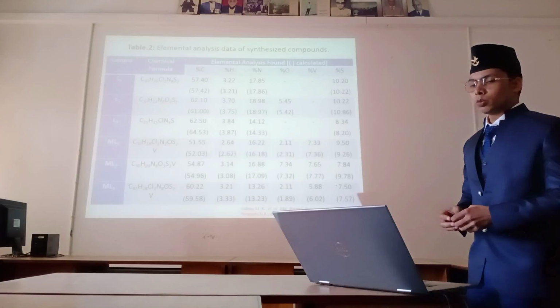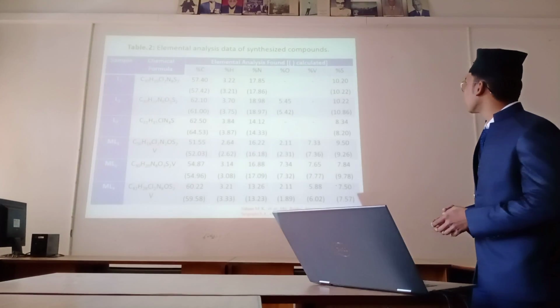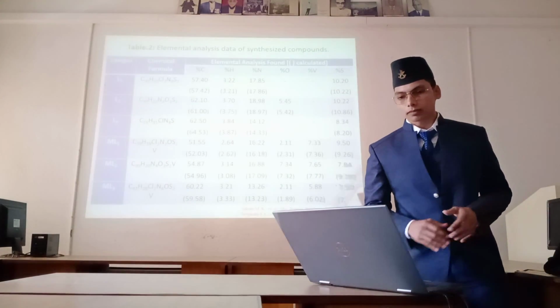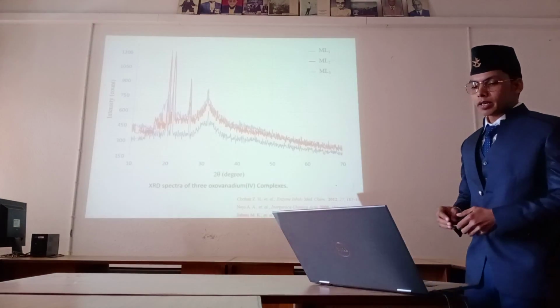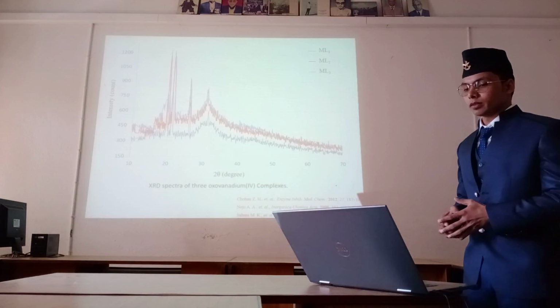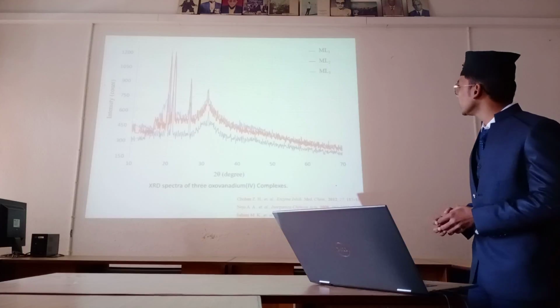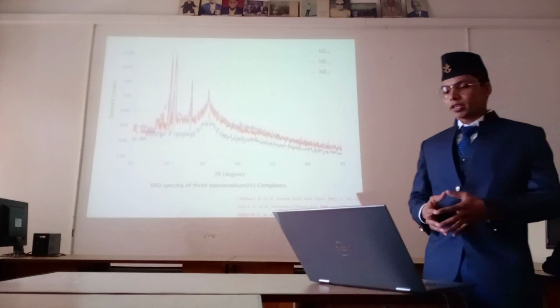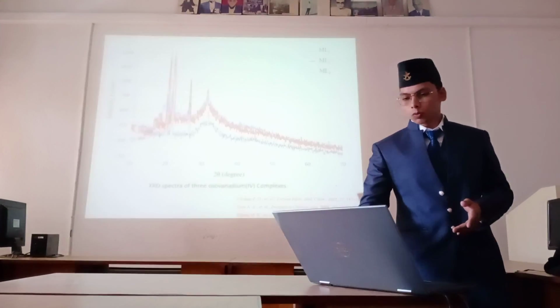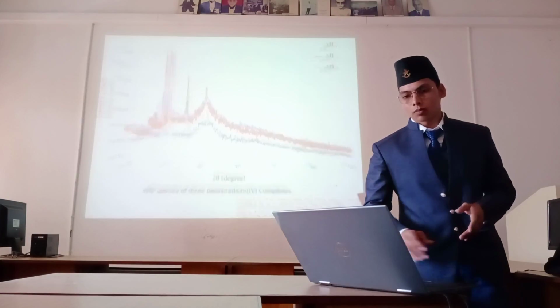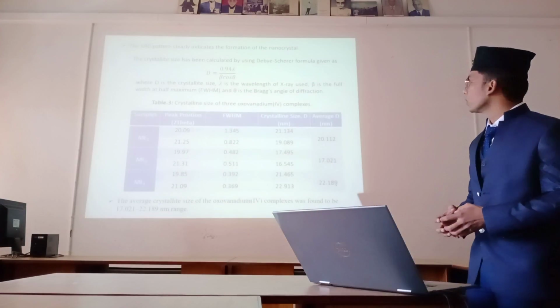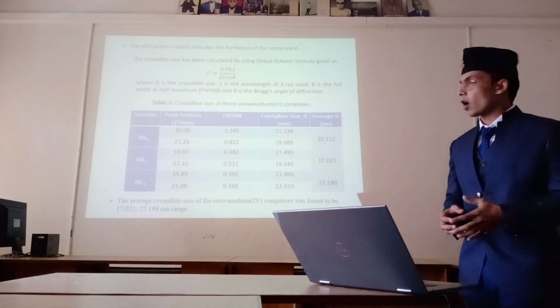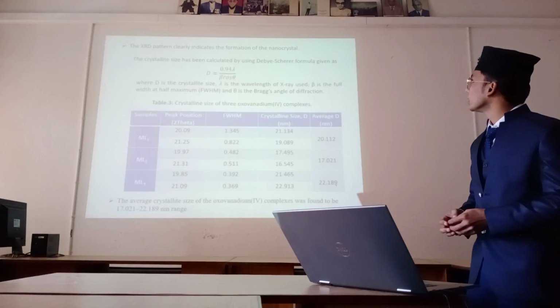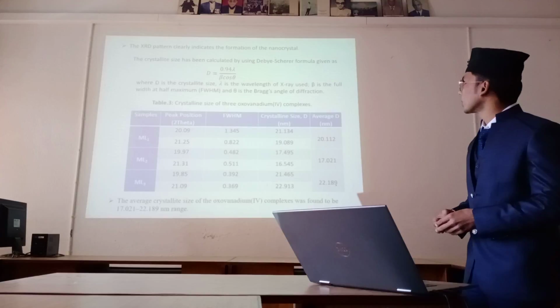This table 2 shows the elemental analysis data for the synthesized complexes. This is the XRD spectra of the 3 synthesized oxovanadium IV complexes. The XRD spectra help us to find out about the phase characterization of the materials. From the XRD spectra of our complexes, it clearly indicates the formation of nanocrystals.